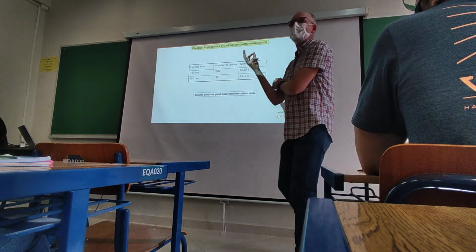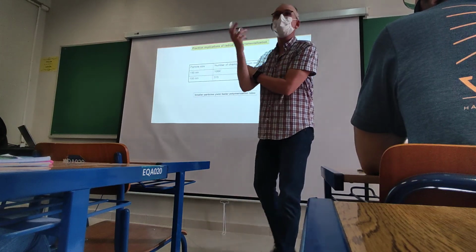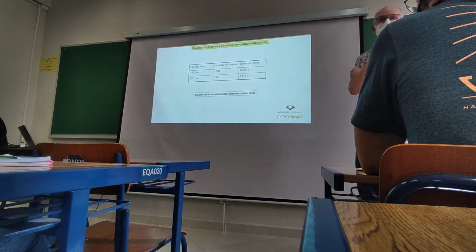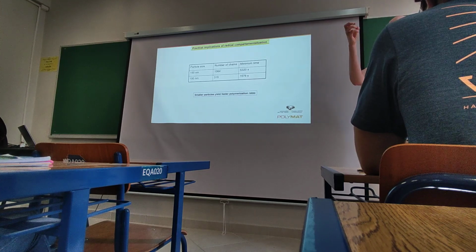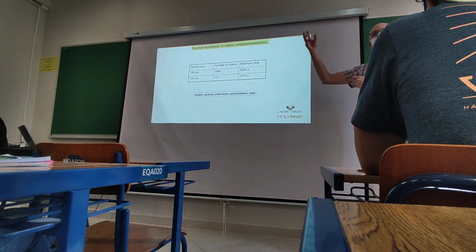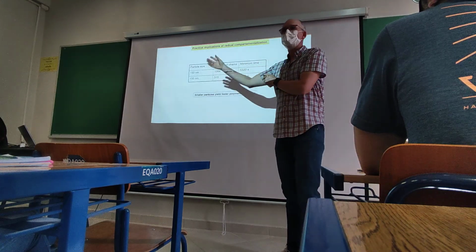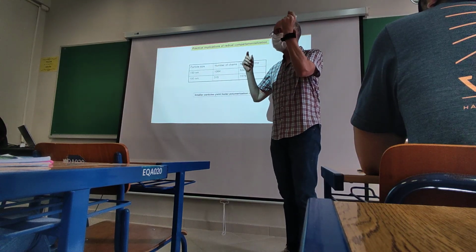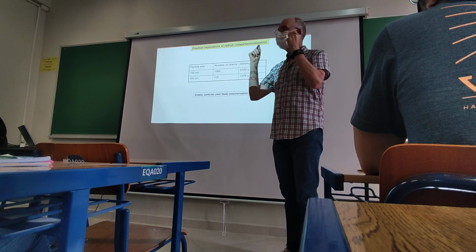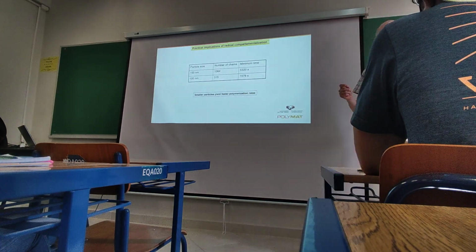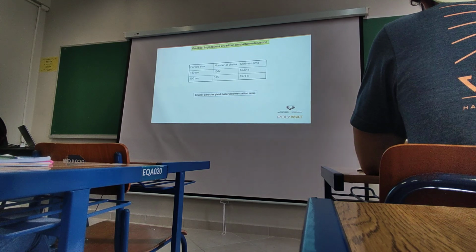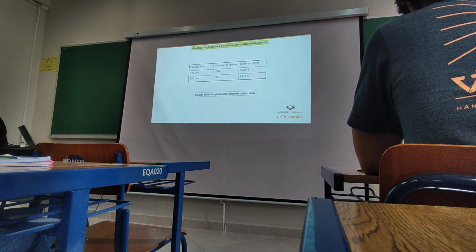Surfactant. So if you change the surfactant, you change the number of micelles that you create. So the higher the surfactant concentration, the higher the number of micelles, the higher the number of particles. So you can control it without touching the temperature or the initiator. You can change the number of particles so that you will obtain more particles, faster reaction and higher molar masses.